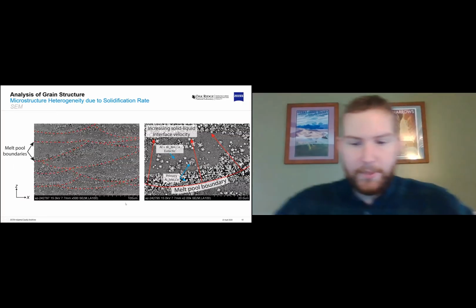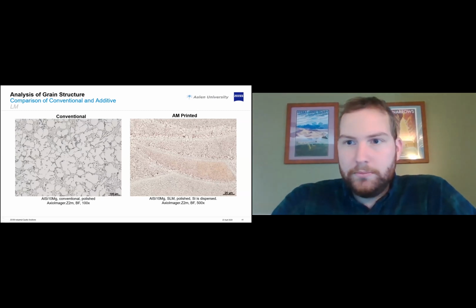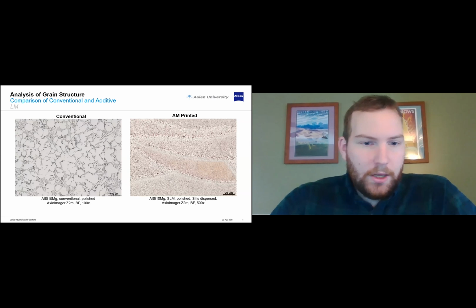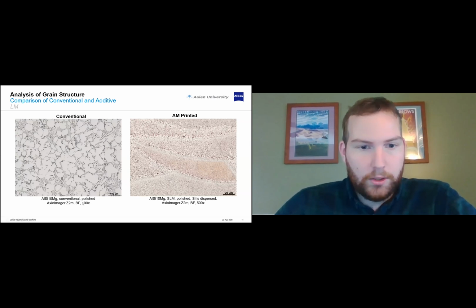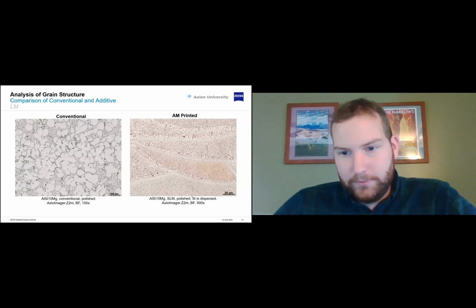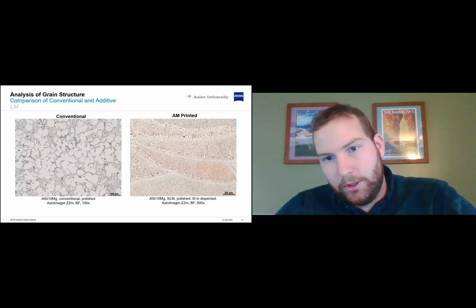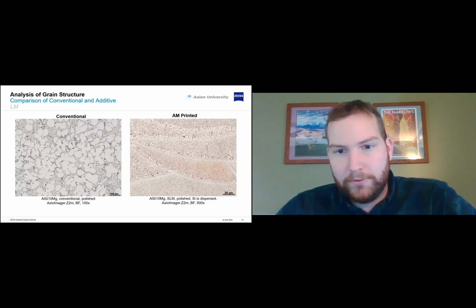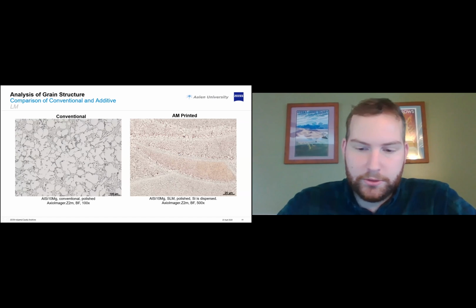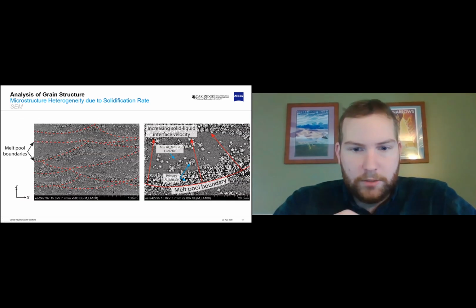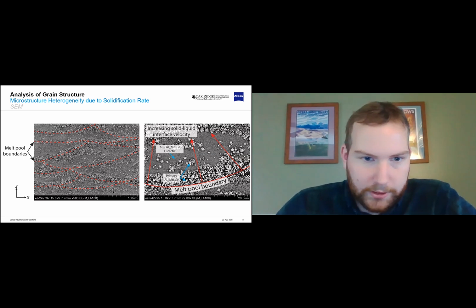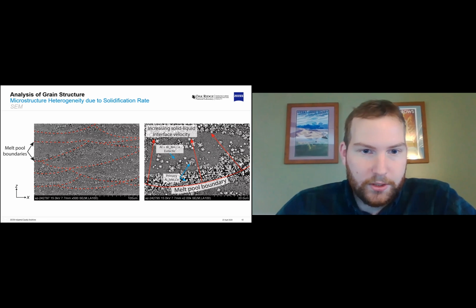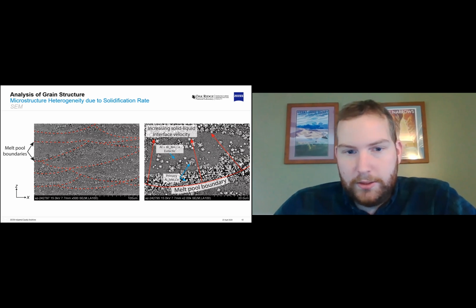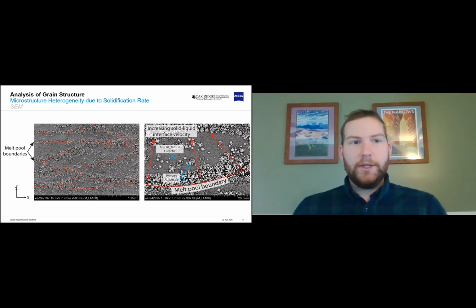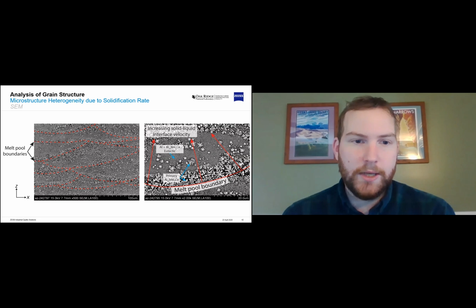So this is a light microscope etched image of aluminum silicon magnesium. This is a conventional sample at 100 times, and you can see the grains very, very clearly here. In an additive, this is at 500 times and they're still really small. And you see these melt pool boundaries, very well defined, separating these grain boundaries too. And this next image is an electron microscope image. You can see you've got a completely different grain structure along the melt pool boundaries versus in the middle. And again, these grains are really, really tiny. So yes, we do see a lot of different grain structures in additive compared to subtractive.